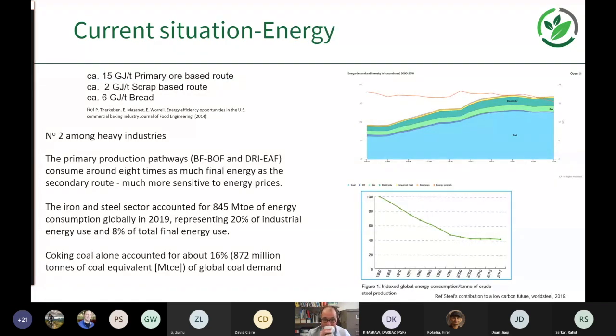So in terms of the energy, primary ore-based production is around 15 gigajoules per ton. So it represents far and away the most energy-intensive of the processes. A scrap-based route is down at 2 gigajoules per ton, so significantly lower energy requirement. And just to put some perspective on that, bread takes around 6 gigajoules per ton. Of course, that's quite a highly processed material.